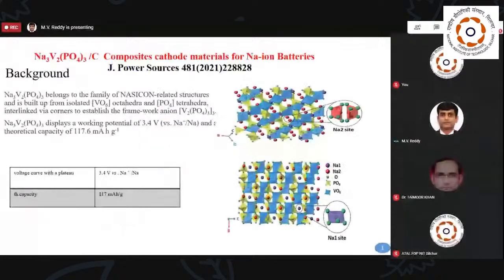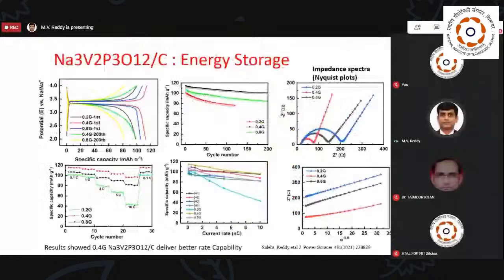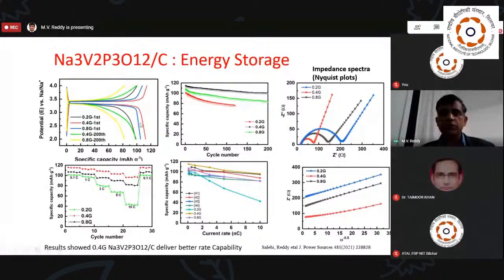I think these are the samples we can present, since I don't have much time. From an engineering point of view, another example is the NASICON-type structures. We've used a carbon coating approach, and with a nice conducting carbon coating it performs reasonably well, nearly 10 C, meaning we can go to fast current rates. The reason is that we checked with impedance again. The impedance analyzer is very useful to see the resistance. Because of the nice carbon coating, we get lower resistance compared to the other material. And you can see the capacity variation, etc.